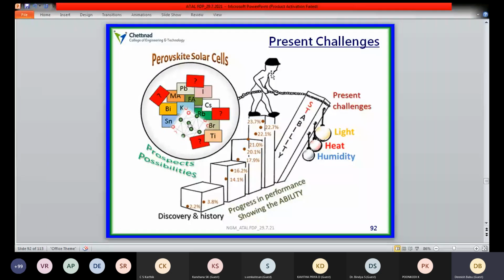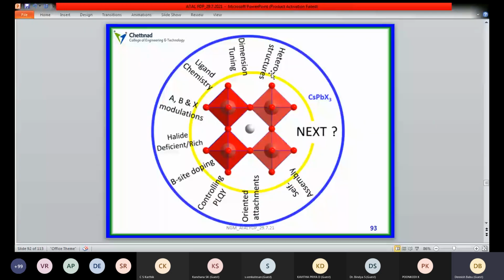And especially in metal halide based perovskite systems, heterostructures, dimension tuning, ligand chemistry, and compositional changes at the A site, B site, and X site, halide deficiency, B site doping, controlling photoluminescence quantum yield, and oriented attachments are already employed. So people are looking for the next approach to tune these perovskite systems to reveal excellent properties from them.